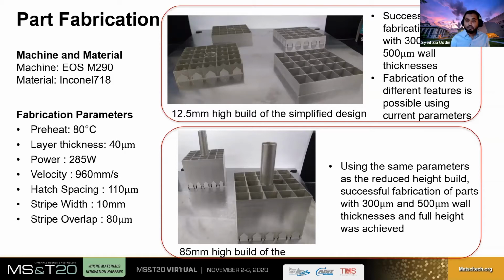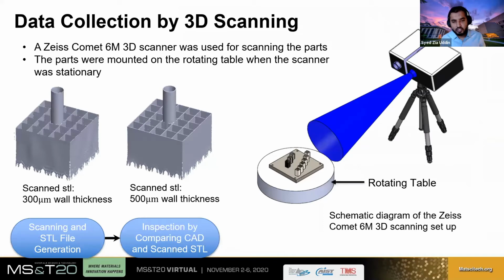So then, after the successful fabrication of these parts using these two different wall thicknesses, we have scanned them using a Zeiss Comet 6M 3D scanner, and we have inspected the scanned STLs by comparing them against our CAD models. At this point, in addition to the 300 micron and 500 micron wall thicknesses, we lowered our wall thickness to 200 micron even, which is not shown here, but we will see the result of that print in a subsequent slide.